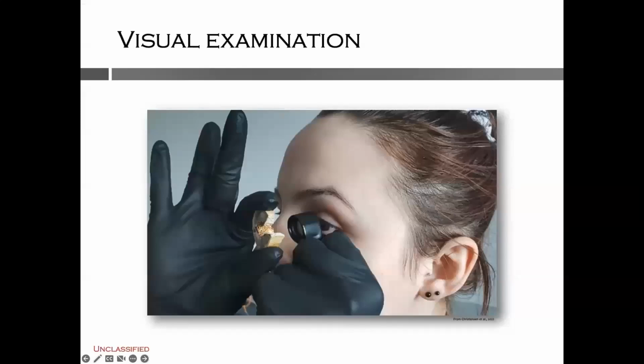Many features of interest in a fractographic analysis are visible with the unaided eye, but depending on what detail of examination is needed, or perhaps the size of the specimen under examination, it may be helpful to use greater magnification or other visualization aids. It is always recommended to begin with unaided visual examination of a bone, and this will include examining each broken piece, the overall cracking and breakage pattern, as well as all of the fracture surfaces. This initial visual examination is important because it allows you to become acquainted with the overall pattern as well as orient the components.